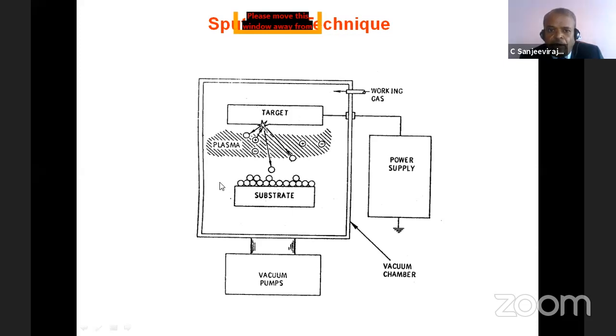And argon is usually easily ionized. That's why people are using argon gas. Or you can use nitrogen. If you take nitrogen, you have to be very careful, because sometimes nitrogen will react with a target material or a source material. In that case, we cannot use nitrogen as a sputtering gas. Therefore, argon is a very good example. Most of the people will be using argon gas, and that argon gas is easily ionized.